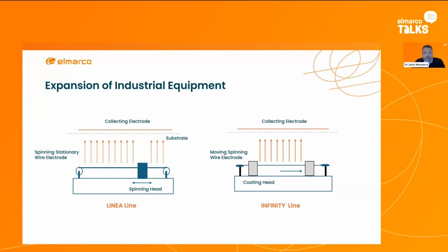That's what our technology has been for the last 10 years or so, or even maybe 15 now, I would say. But if you look at infinity technology, that's where we're actually now moving the wire very, very rapidly through the process. So we're coating it on one side. It's like a loop. We coat it on one side, we clean it on the other side, but both sides of the loop, when it's passing through, let's say, the spinning zone, is coated with solution, and that solution spinning. So it's the same process, same physics, same technology.